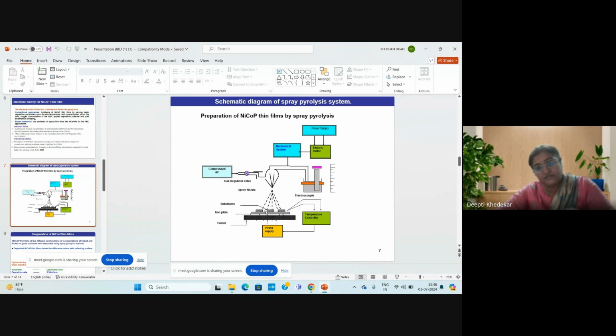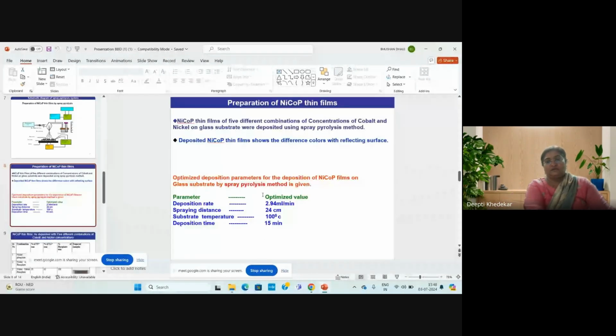We use a glass substrate over here, and then a heating iron plate is there. Temperature of the plate is 100 degrees. Some parameters of this apparatus are shown over here. We prepared 5 different combinations of cobalt and nickel concentration on the glass substrate, and the deposited NiCoP thin films show different colors with reflecting surfaces. Parameters of the method are: deposition rate 2.94 ml per minute, spraying distance 24 centimeters, substrate temperature 100 degrees Celsius, and deposition time 15 minutes.